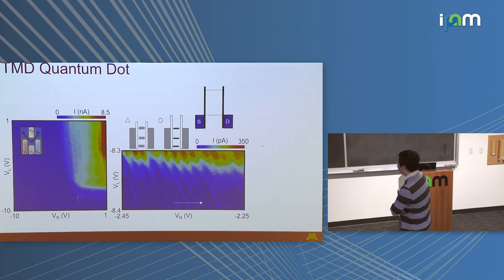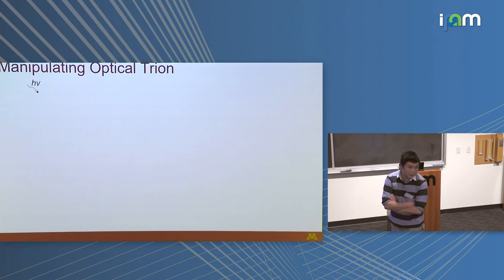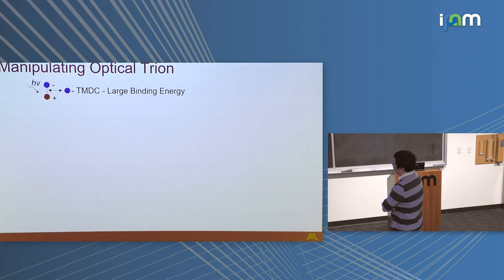You have the SET behavior, Coulomb blockade, but this is something for the first time in any material that you cannot do in gallium arsenide. If you hit this semiconductor with a photon, you can generate an electron-hole pair temporarily. This is called an exciton. If you have a free electron nearby, that is basically the electron in my quantum dot, it forms a trion state. We're interested in the trion state because it's not charge neutral, so you can still hope to confine it with the electrostatic potential. In transition metal dichalcogenides, they simply have a much larger binding energy than gallium arsenide,